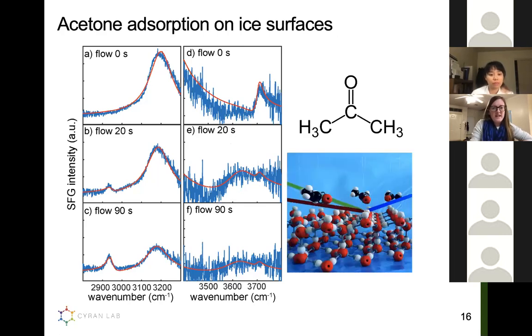So what we could tell from these experiments is that, one, we could see that acetone was absorbing onto the surface, and two, we could get out some information about how the acetone was interacting with the ice surface. So in this case, we have these OH vibrations at the surface, right? And the reason that this is shifting to lower frequencies is that you now add the acetone. The acetone starts to hydrogen bond through the carbonyl group to the ice surface, and then it shifts this frequency. And so we could see the acetone absorption and how it's interacting with the surface specifically with sum frequency generation spectroscopy.